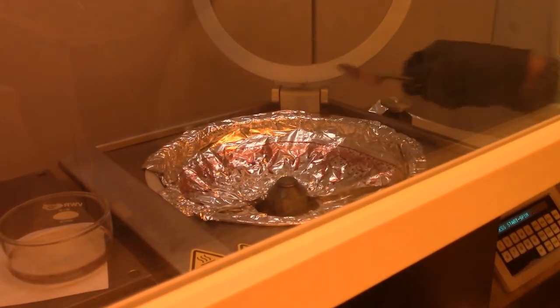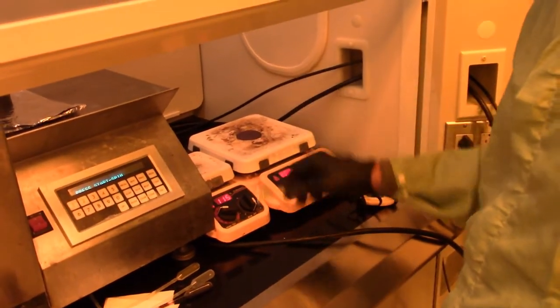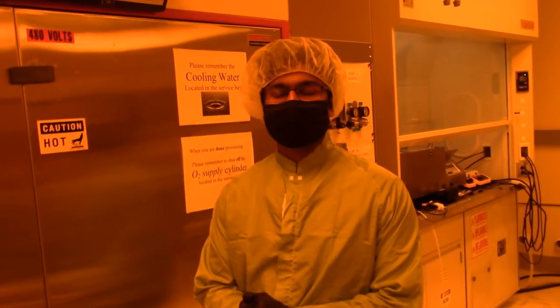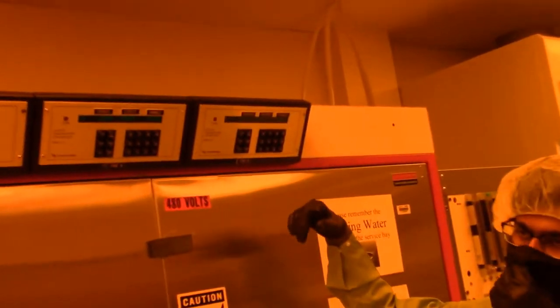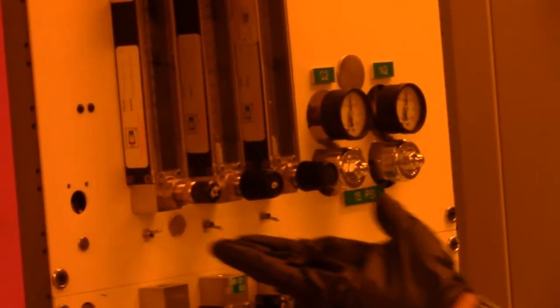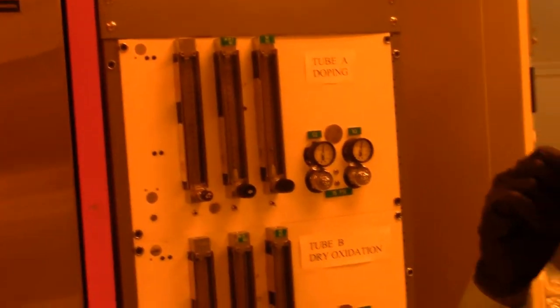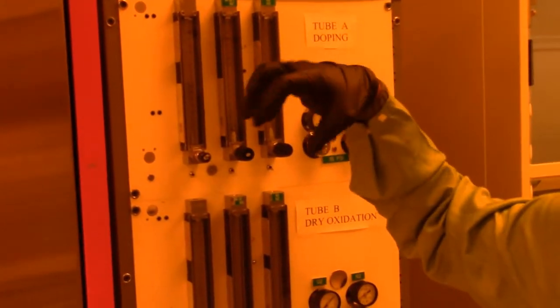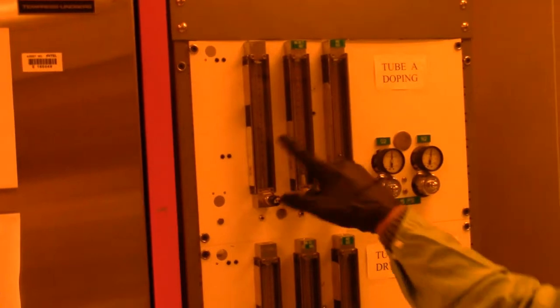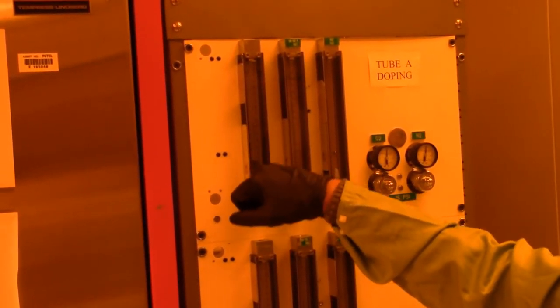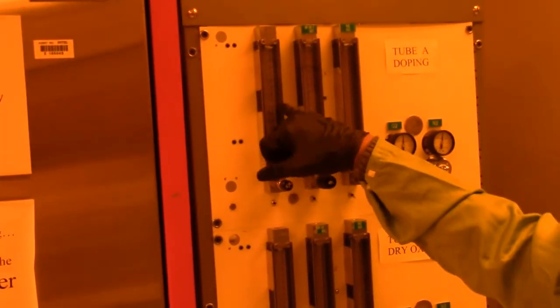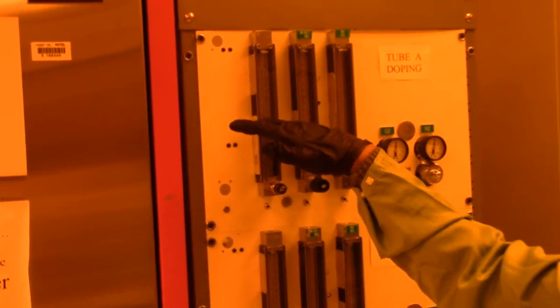We can go ahead and quickly bake it on a 200C hot plate for 10 minutes. For diffusion, we'll be using tube A, which is at 1100 degrees centigrade, as you can see. We'll also be flowing a mixture of two gases, that is low flow oxygen and nitrogen. Low flow oxygen is at around a setting of 70, and high flow nitrogen is around a setting of 19.5. So you can see that this process actually drives in the phosphorus dopants. As a consequence of flowing some oxygen, you will also grow some oxide, but you can remove this oxide later on in the next step and measure the resistivity of the diffusion that we have created.